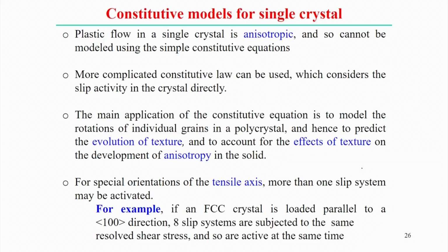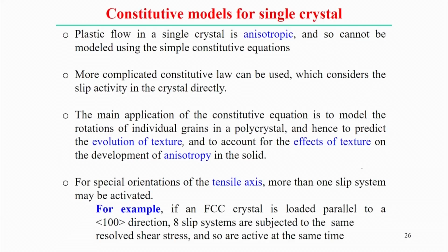Let us look into that example. For a special orientation of the tensile axis, more than one slip system may be activated. We have already explained that, at least in the ideal condition, at least 5 slip systems will be active to maintain the compatibility condition in the deformation of a single crystal structure. So for example, if an FCC crystal is loaded parallel to the 1, 0, 0 direction, that is any one of the axes of a unit cell, 8 slip systems are subjected to the same amount of resolved shear stress and so are active at the same time.